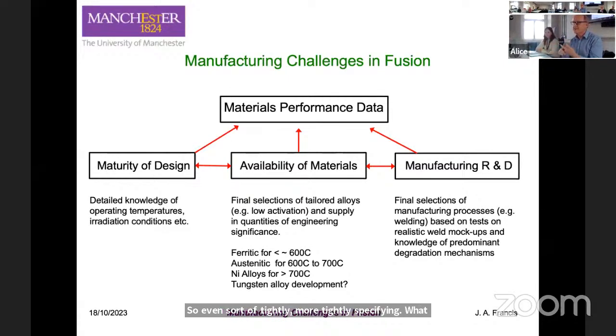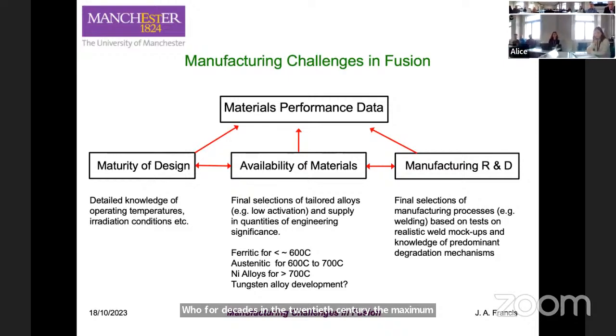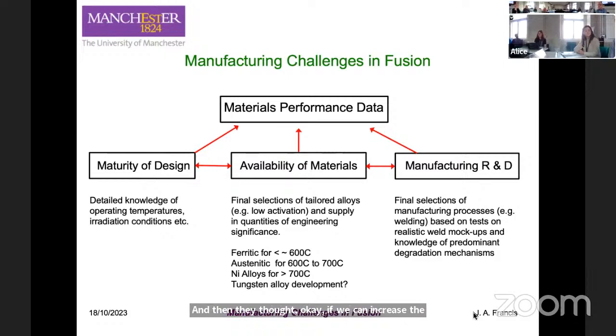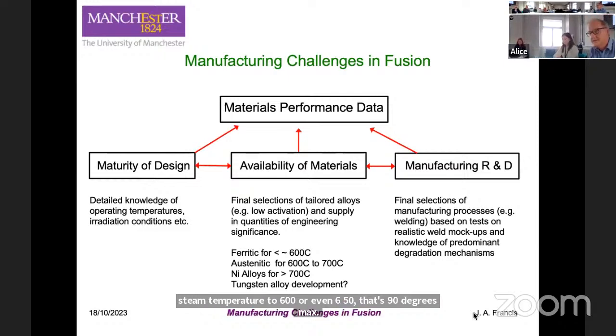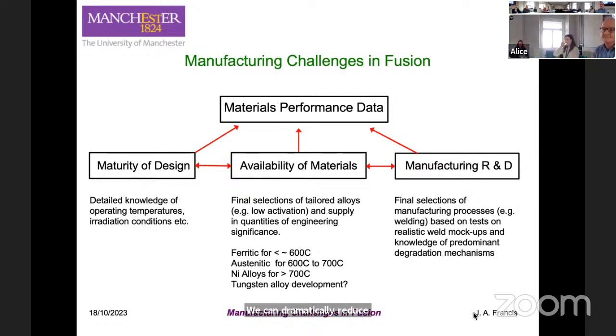Because as I say, a change of 50 degrees means a change of alloy, means a change of joining process, means a change of the range of microstructures that you're going to see. Now, just by way of example, going back to the fossil-fired power sector, for decades in the 20th century the maximum steam temperature was 560 degrees C. 2.25 chromium, 1 molybdenum steel was the workhorse steel. And then they thought, okay, if we can increase the steam temperature to 600 or even 650, that's 90 degrees max, we can dramatically reduce carbon emissions and get a greater thermal efficiency out of our plant.